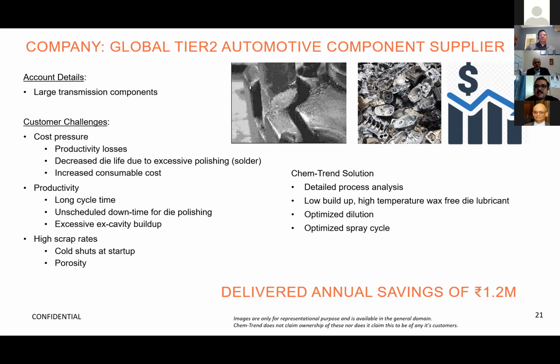So we did a detailed process analysis of the whole process, and we ended up reducing the cost on the consumables. We used a low buildup, high temperature, wax-free die lubricant technology, which enhanced the solder protection on the die. In turn, the customer went from polishing every 2 hours to polishing once every 8 hours a day. So a significant improvement for the customer.